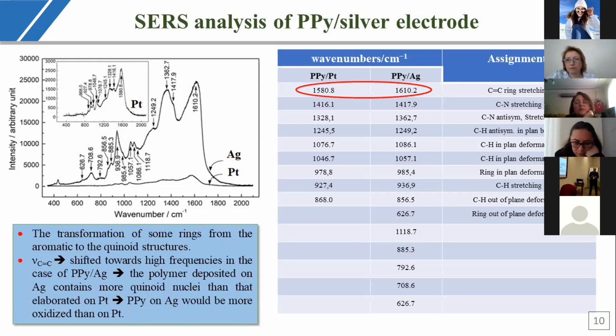The main band at 1610 cm-1 is assigned to C=C ring stretching. As known, the transition between the reduced and oxidized state of polypyrrole is accompanied by the transformation of some rings from aromatic to quinoid structure. And according to some authors, the frequency of the C=C vibration in the quinoid nuclei is higher than that of aromatic. Therefore, in our case, this band is shifted toward high frequency in the polypyrrole silver system, so the polymer deposited on silver contains more quinoid nuclei and is more oxidized than that elaborated on platinum.